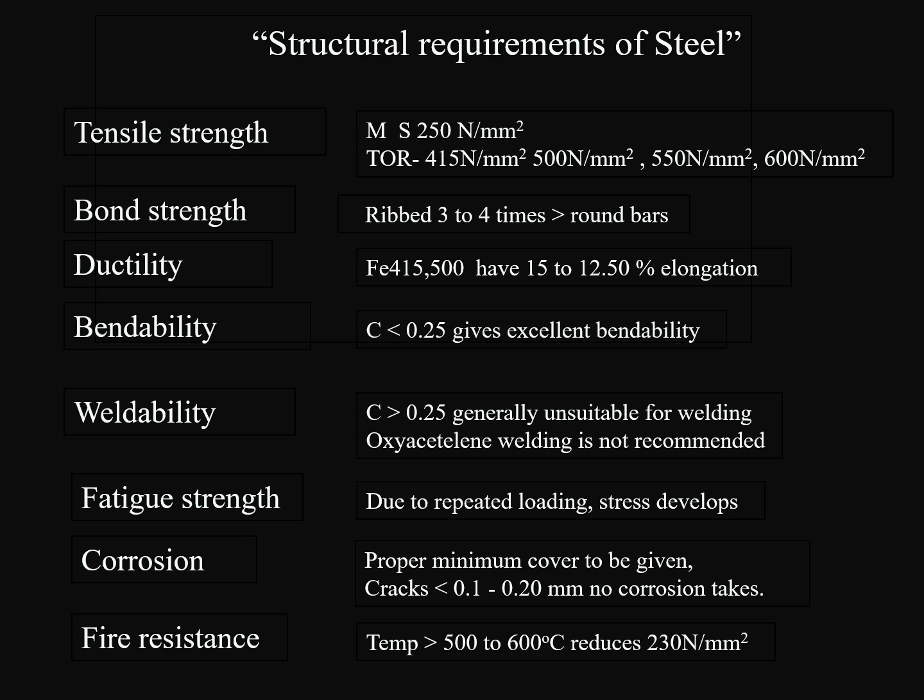Corrosion. Proper minimum cover is to be given to avoid corrosion in RCC structures. Cracks in RCC structures, if less than 0.1 to 0.2 mm, there will be no corrosion, because the ingress of water and oxygen requires a little more thickness of cracks, which may lead to corrosion of